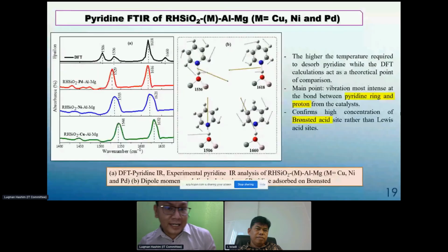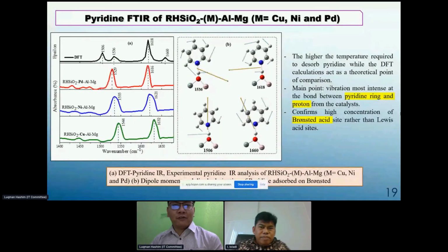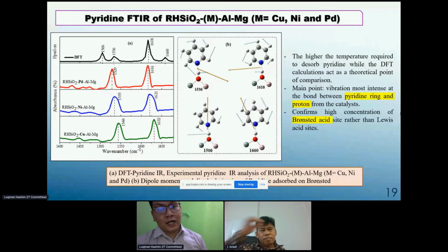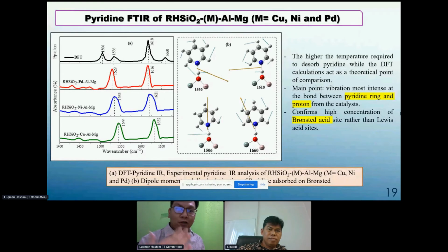So very briefly for pyridine FTIR, what we want to find out is which kind of acid we are dealing with, Bronsted or Lewis. So briefly, if we compare the experimental and theoretical values here, the DFT graph on the left-hand side there is the theoretical value. The peaks at 1536 and 1618 in the middle are the ones representing Bronsted. So I think you can all guess what I'm trying to get at: comparing that to our experimental results, we are dealing with Bronsted acidity mainly here. And as our simulation is shown there, those are images of the simulation.